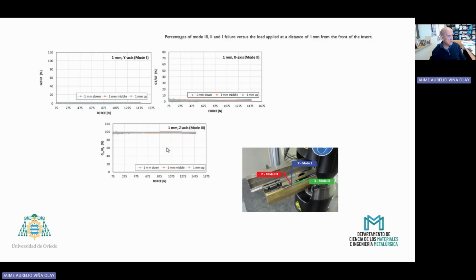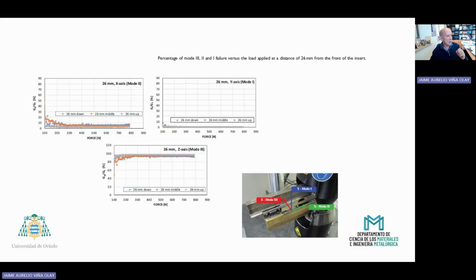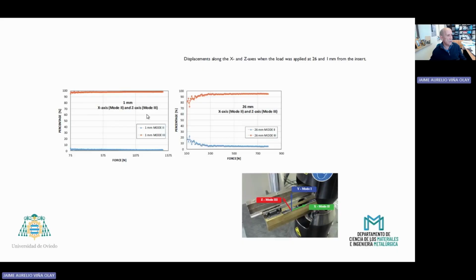In this slide, we present the results of the mode 1, mode 2, and mode 3 that we obtained in a point at a distance of 1 millimeter from the front of the insert. Here is the same, but at a distance of 26 millimeters. And here we can compare the results at 1 millimeter and 26 millimeters. With the red color, with the orange color is mode 3, and blue color is mode 2.